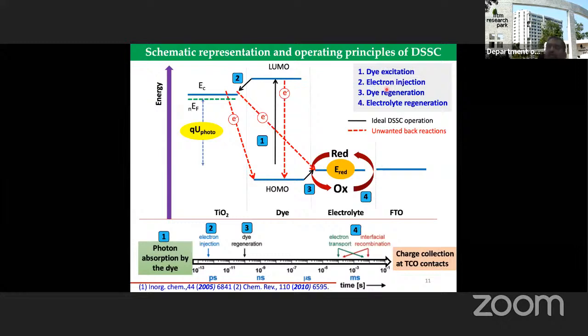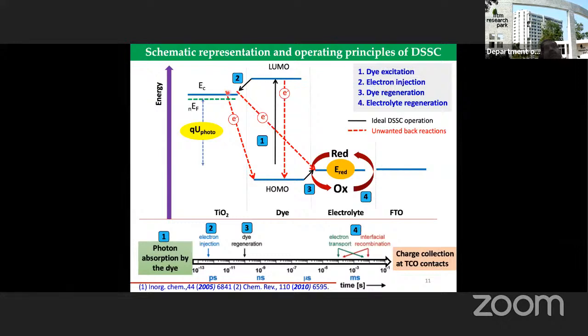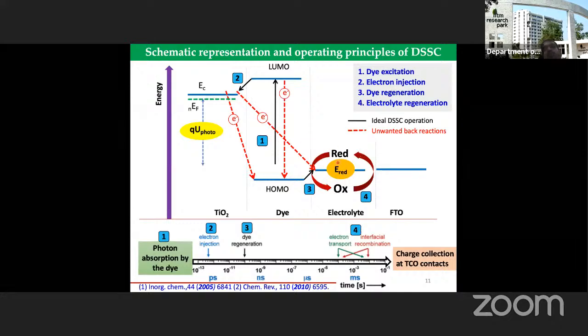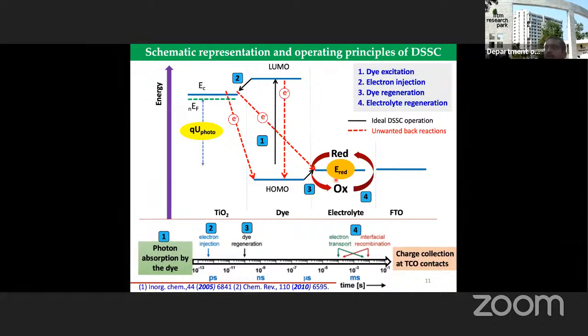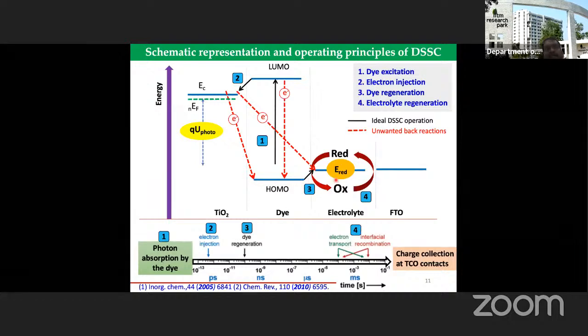These are the ways by which back electron transfer happens, which is actually not good, because if this happens, we will not be able to harvest the light, as the electron is not going to come in the external circuit. Therefore, this quenching or back electron transfer process should be avoided. So we need to design dyes whose LUMO is close to the conduction band, design electrolyte whose redox energy is close to the HOMO of the dye, and do molecular architecture of the dye such that these back electron transfers are prevented to some extent. If we can achieve these three, we'll be able to make a solar cell which is high voltage, well performing, and able to capture most of the sun's spectrum.